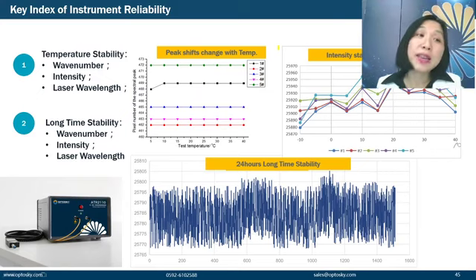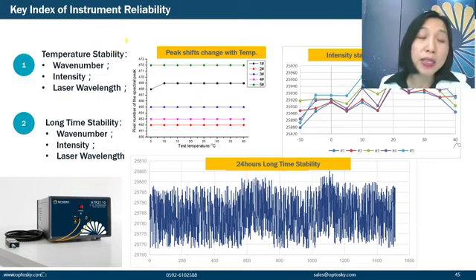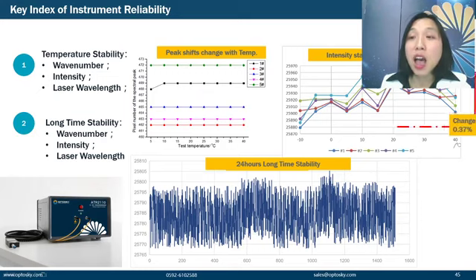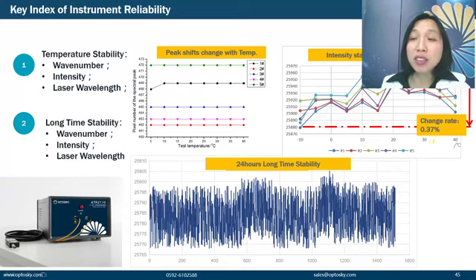As we have already mentioned before, Optosky has very good instrument reliability. How can we prove that our instrument reliability is good? Firstly, we have the peak shift change with temperature experiment, and our temperature stability is very good in wavenumber, intensity, and laser wavelength. And the intensity stability change with temperature, our intensity change rate is only 0.37%. That is very low in the industry.